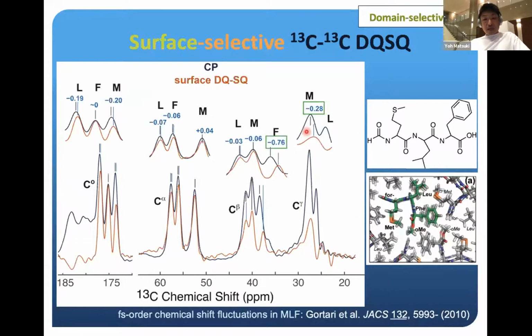The site-specific peak shifts result from some kind of perturbation on the peptide conformation, might be related to some loosening of the crystal or a change in the crystal packing or crystal strain at the surface region, leading to a distinct time average of this fast, rapidly fluctuating chemical shift, as has been suggested in simulation work on MLF crystals. Although it is kind of difficult to quantitatively describe what kind of peptide conformation change has happened at the moment, because the change is a little too small.